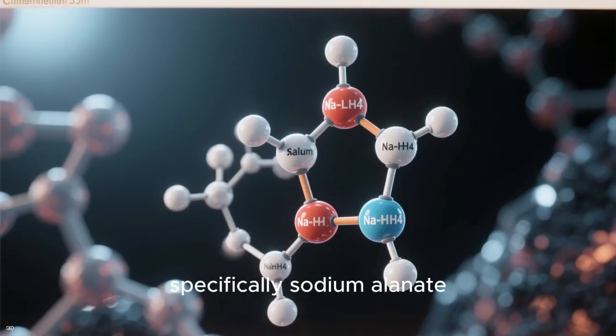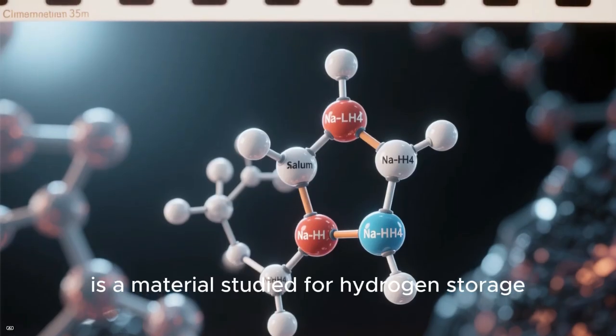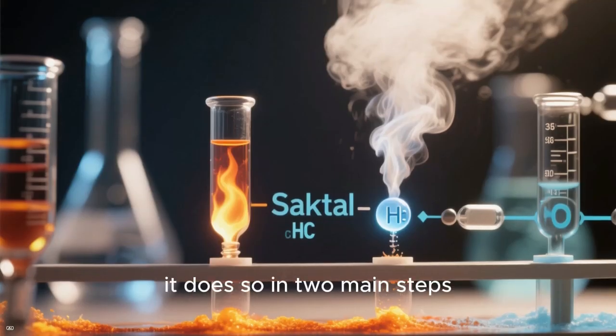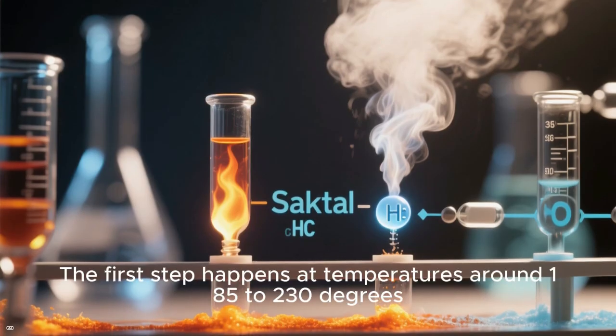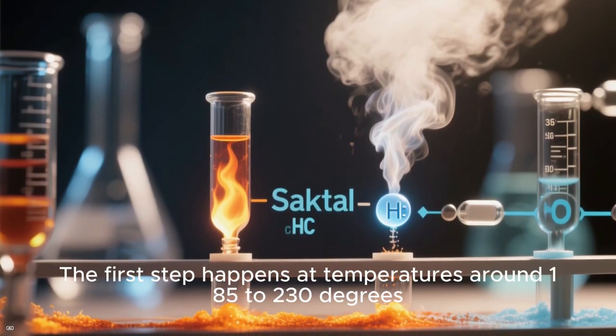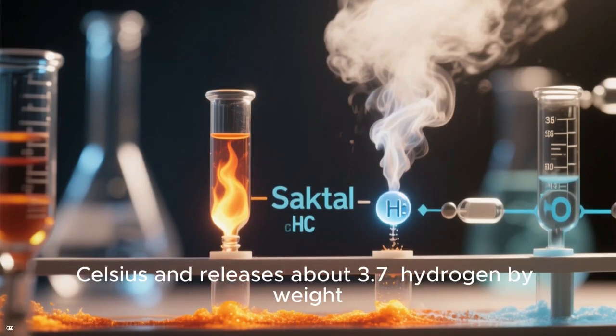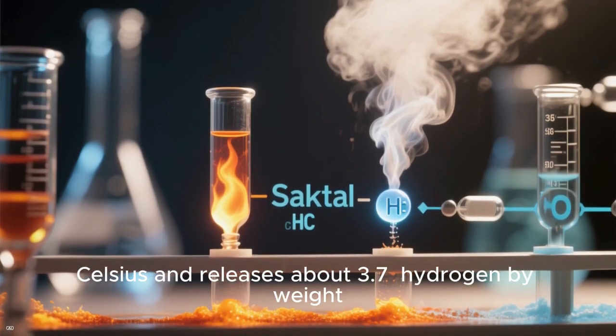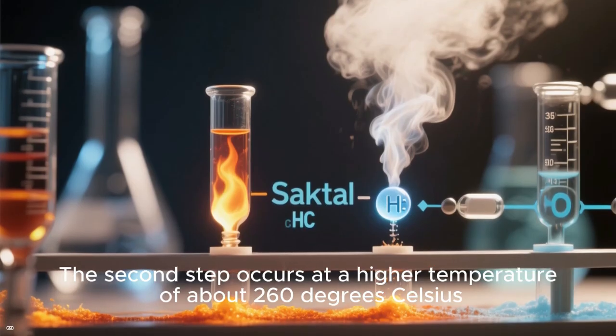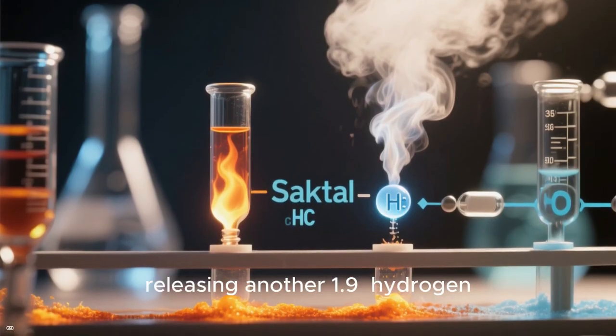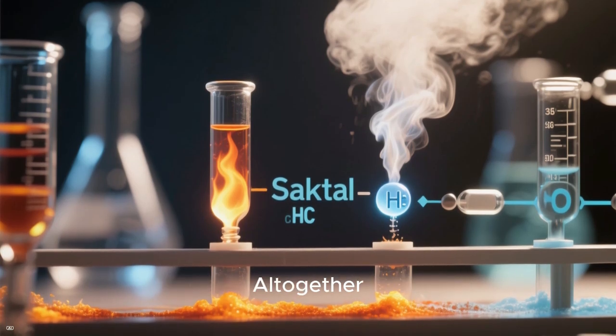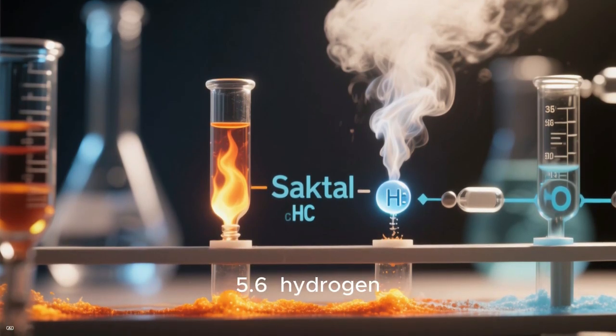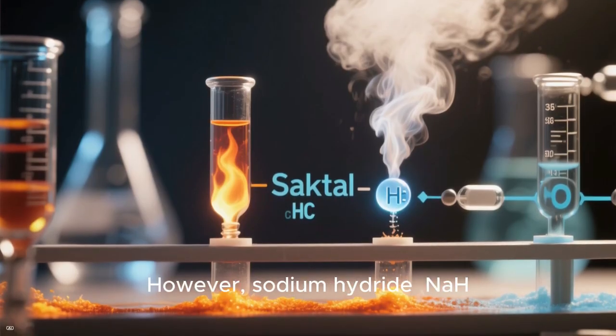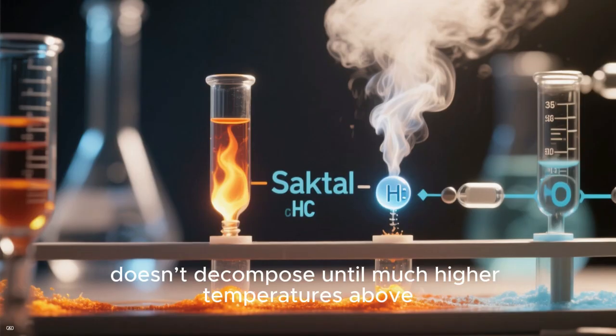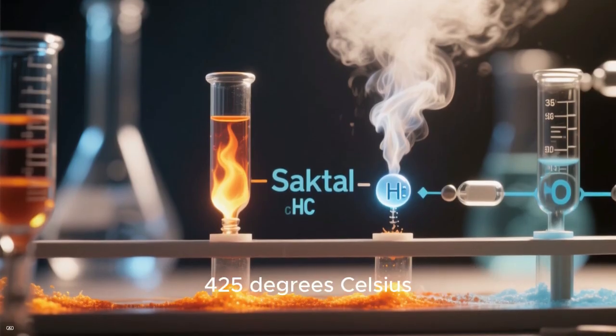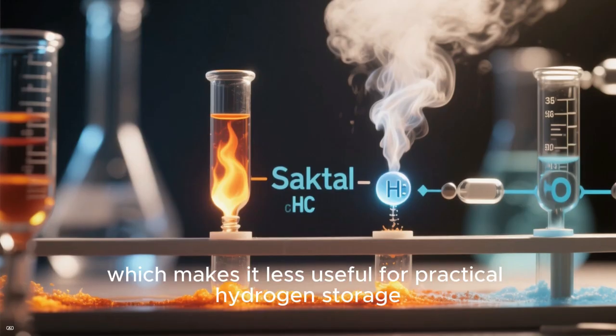Aluminum hydride, specifically sodium alanate (NaAlH4), is a material studied for hydrogen storage. When NaAlH4 breaks down, it does so in two main steps. The first step happens at temperatures around 185 to 230 degrees Celsius and releases about 3.7% hydrogen by weight. The second step occurs at a higher temperature of about 260 degrees Celsius, releasing another 1.9% hydrogen. Altogether, NaAlH4 can release roughly 5.6% hydrogen. However, sodium hydride (NaH), a product of the breakdown, doesn't decompose until much higher temperatures above 425 degrees Celsius, which makes it less useful for practical hydrogen storage.